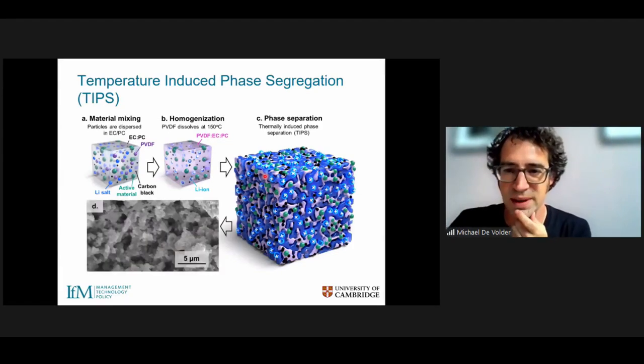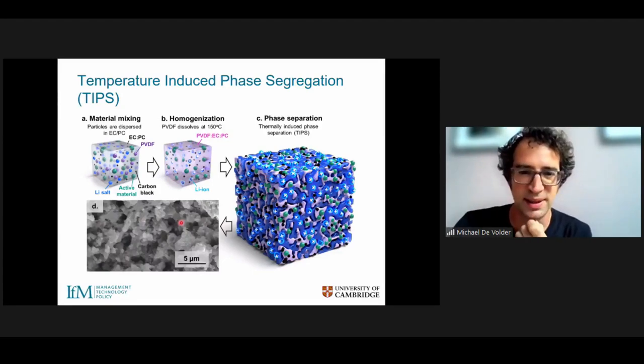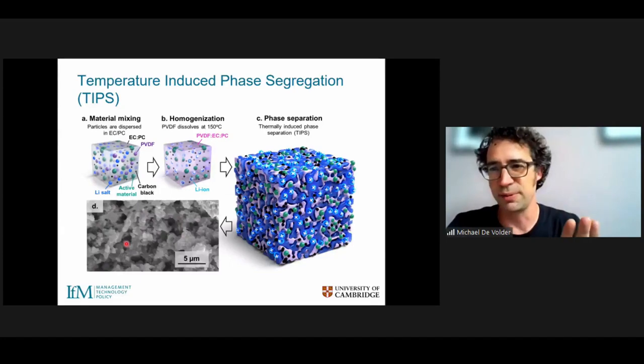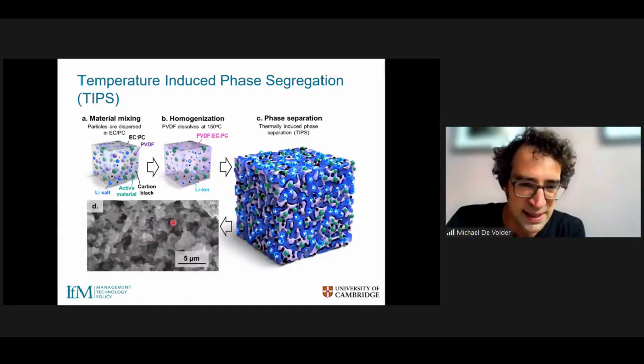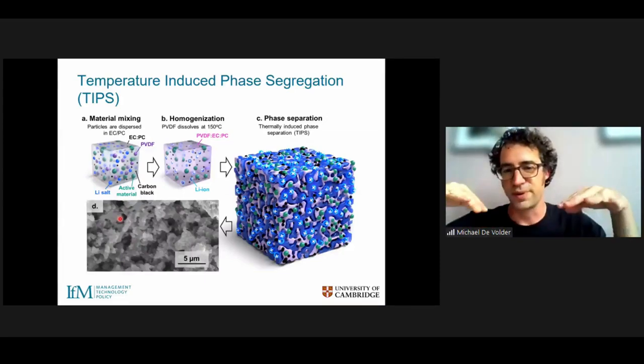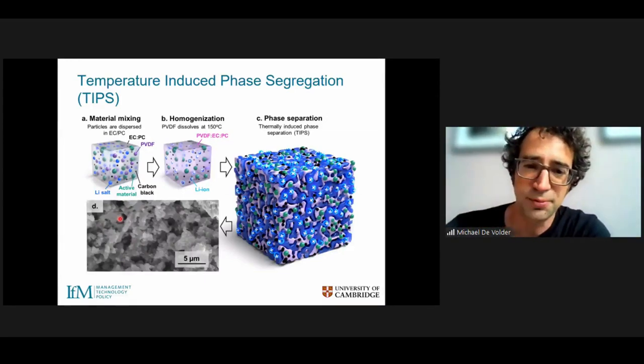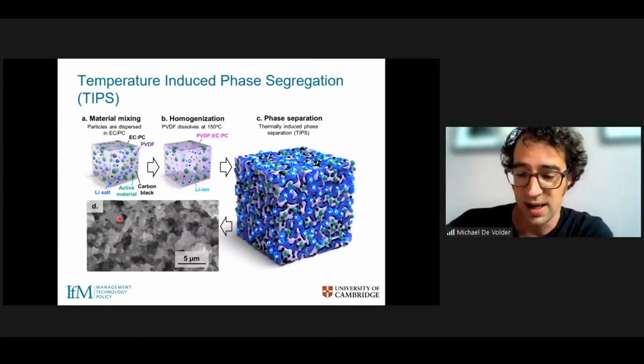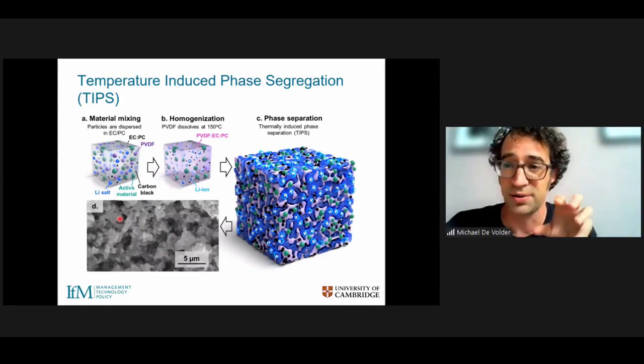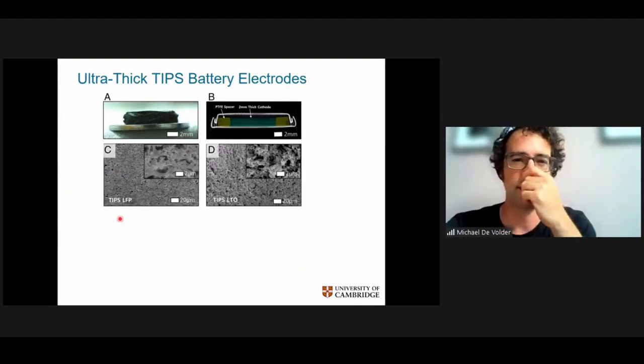And so if you would carry out this experiment and then take the battery material and look at it after drying and removing the electrolyte, I'm not sure if you can see it well on the screen, but you can see some black holes here, which is actually the holes formed in the bicontinuous network as a result of the TIPS process, and that allows for the lithium ions to move through your electrode.